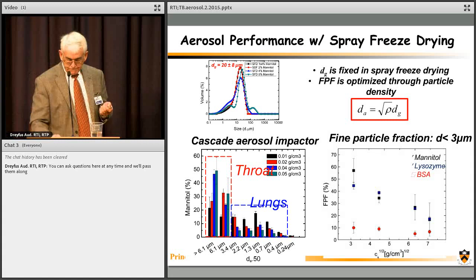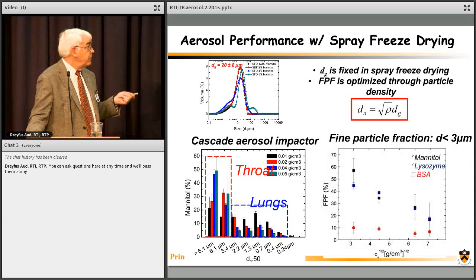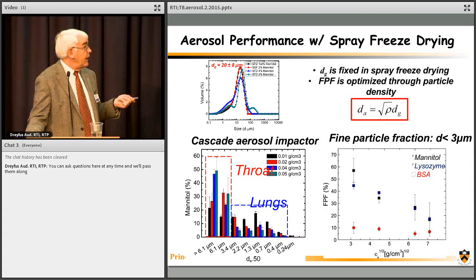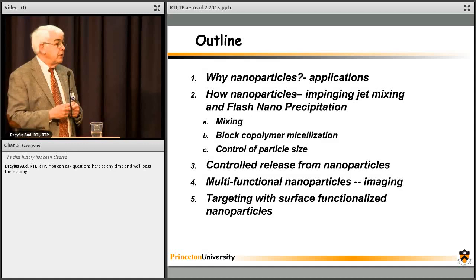This is the fine particle fraction, so these will be things under 3 microns. This is the constant square root of concentration as predicted by that. And so you can see for the lysozyme and mannitol, it follows this square root dependence. BSA doesn't, because the BSA particles are sticky towards each other, and so you never get a fine particle fraction. They don't aerosolize easily from the inhaler. They're too sticky towards each other.